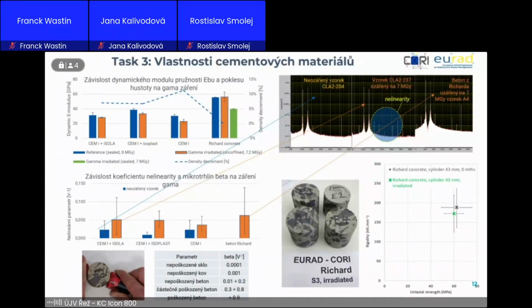When there was a sample without irradiation, the small slab of this size, there are no special peaks. The sample with irradiation has some peaks, and this sample from the Richard repository also has peaks. More or less, it says that there are non-linearities and some cracks, microcracks. But concrete is not a simple material, and if I cast concrete and prepare a sample, there may be some crack, some non-linearity.